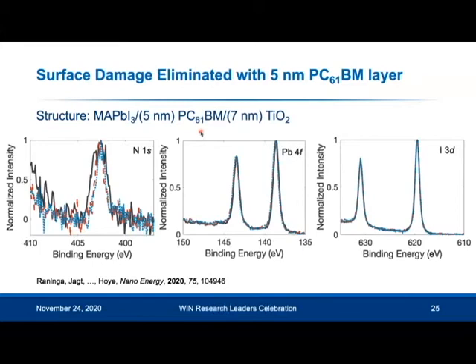So to look at the buried perovskite interface, we thinned down the PCBM layer by decreasing its concentration when we solution processed it. And that meant that this is a nominal thickness, but we had some regions as well where the thickness was much less than this, and therefore the total thickness of the overlayers was small enough that we could see through them with the XPS and look at the buried perovskite interface.